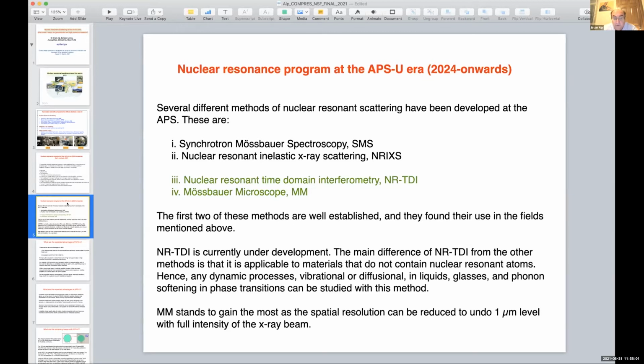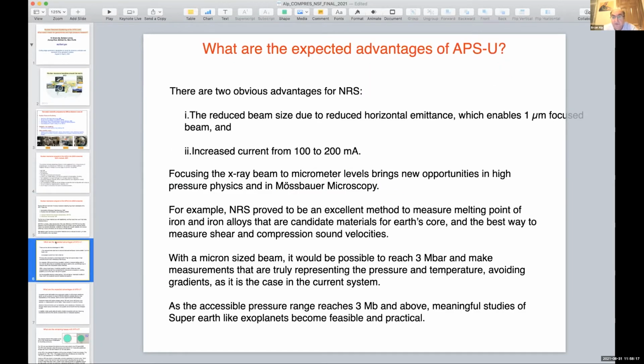So Mössbauer microscopy and TDI will gain most, because Mössbauer microscopy will gain because the spatial resolution can be reduced to under 1 micron level with full intensity of the X-ray beam. So there are two obvious advantages that you can imagine in the APS-U for nuclear resonance scattering. One would be the reduced beam size due to the reduced horizontal emittance, which we will be able to go under 1 micron beam. The other one is the increased current from 100 to 200 milliamp.